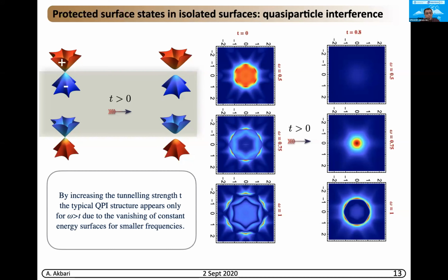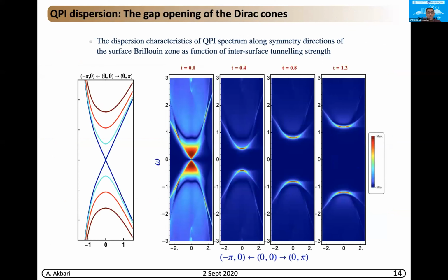So also, we can look at the dispersion of the QPI feature. On the left-hand side, I show the dispersion for the original model for two certain momentum directions, from 0, 0 to minus pi, 0, or 0, 0 to 0, pi direction. And on the right-hand side, if I run the QPI calculation, you can nicely see the similar dispersion also in the QPI feature. The only difference is that the momentum in the dispersion is wider by a factor of 2. So you see that by going to the higher hopping, or increasing the gap in the system, this gap also appears in the QPI feature and can be detected in future experiments.